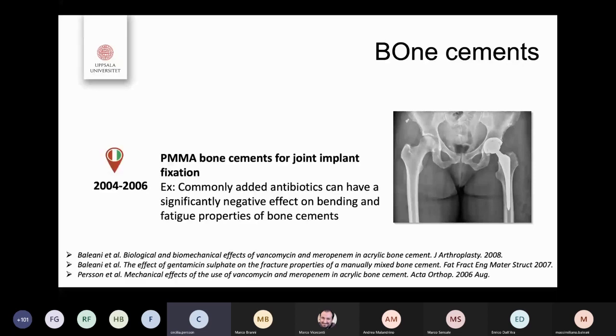So bone cements, we've already heard a bit about bone cements today. Of course, you can use these to fix joint implants, and that is what we did, and those types of cements that we looked at. And Marco mentioned briefly as well that one of the things we did was to look at the effect of the addition of different antibiotics to the bone cements, because this is something that several surgeons did in the operating theater. You added commonly used antibiotics directly to the cement, and it wasn't really known what effect this had on the mechanical properties. And we showed in a few studies that some of the antibiotics, vancomycin for example, could have a significantly negative effect on important mechanical properties of the bone cements.